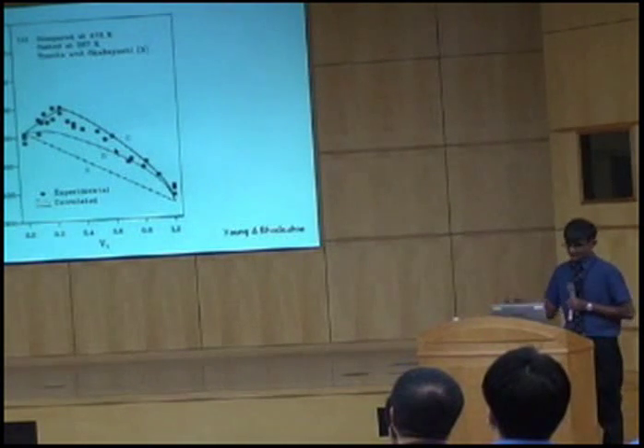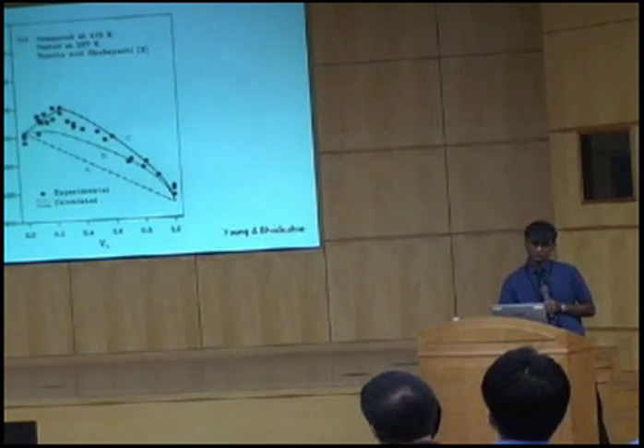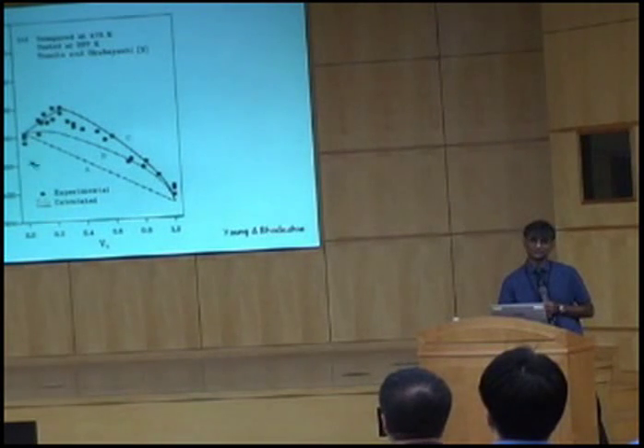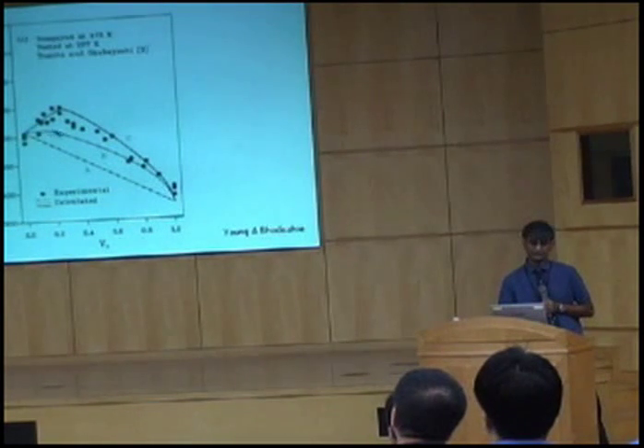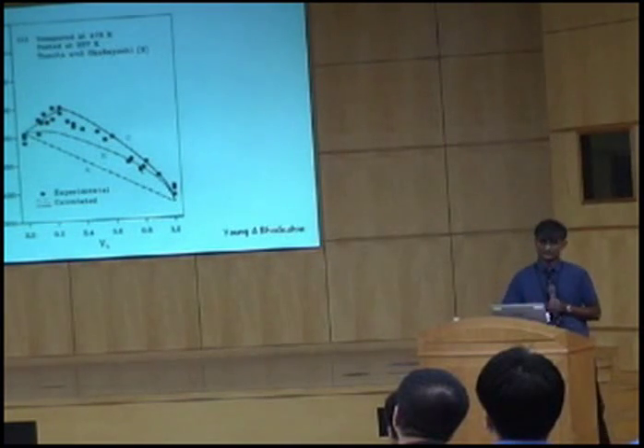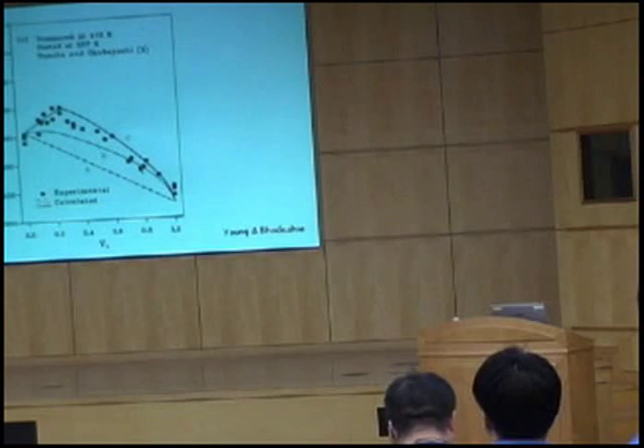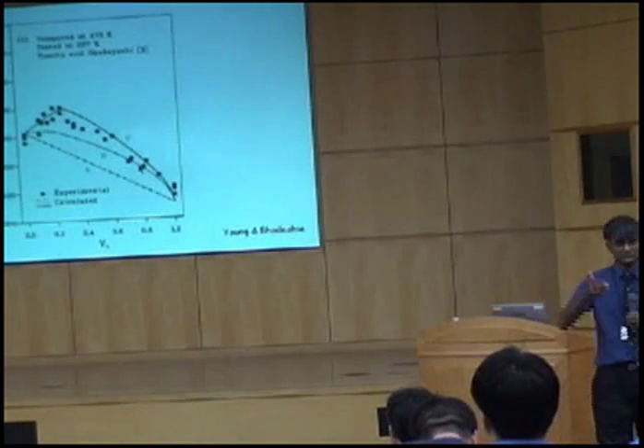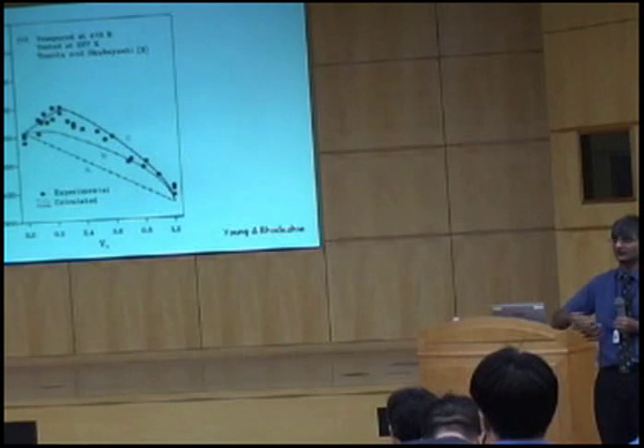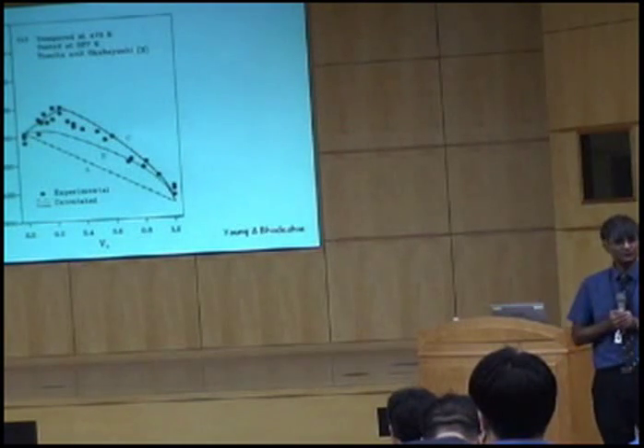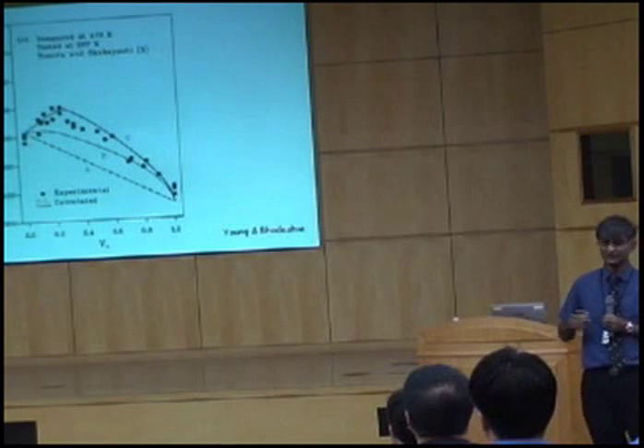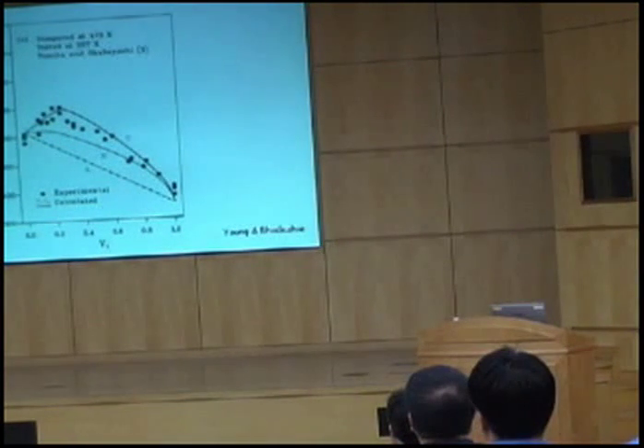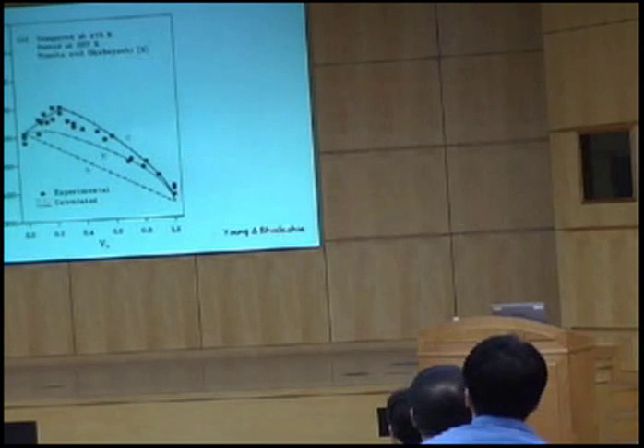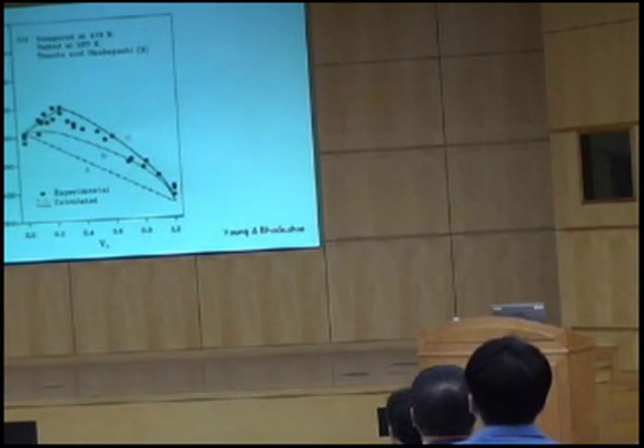And here are those same experimental data that I showed you earlier. This is the rule of mixtures, okay, which clearly doesn't reproduce the experimental data. This is allowing for carbon partitioning, and this is allowing for carbon partitioning and the plastic constraint. And you can see that I don't need to use a complicated finite element model. I can just use that master curve for constraint and the partitioning of carbon, and the data are reproduced pretty accurately. Okay? So we can't simply use a rule of mixtures when we are dealing with a soft and a hard material together, like a dual phase steel, for example.